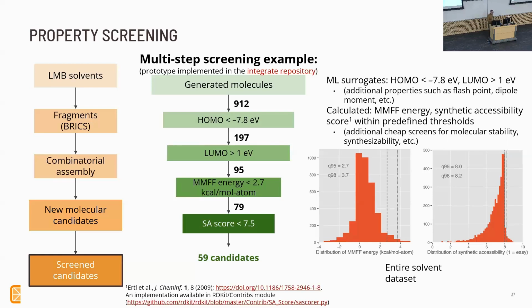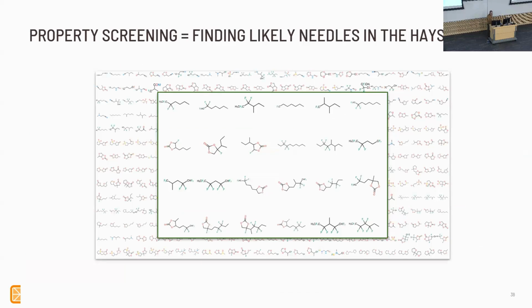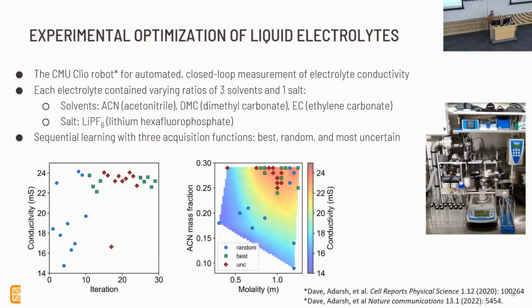And then of these, we ran some very simple calculations and simulations on energetic calculations, like what are their total energies based on things like steric hindrance and whatnot. You can roll those out, or dangling bonds or things like that, and synthesizability. And then we ended up with a pool of about 59 that we were able to pass all these screens. And now we found basically the likely needle in the haystack with this process. And so we did do some experimental optimization of these electrolytes.